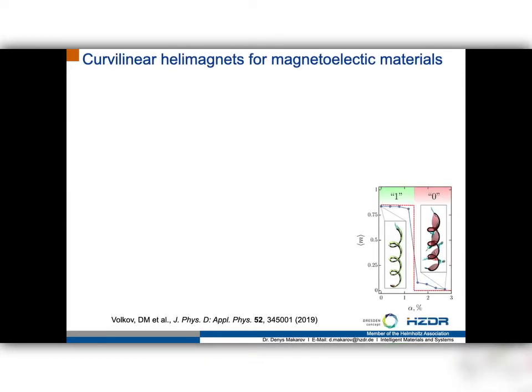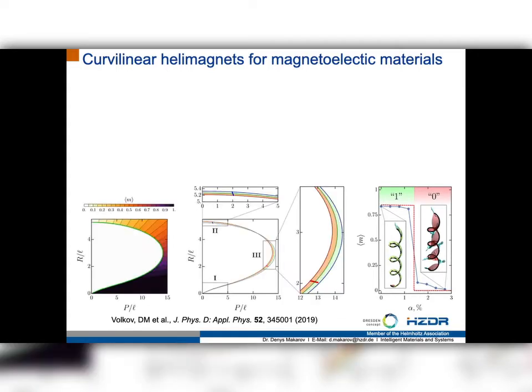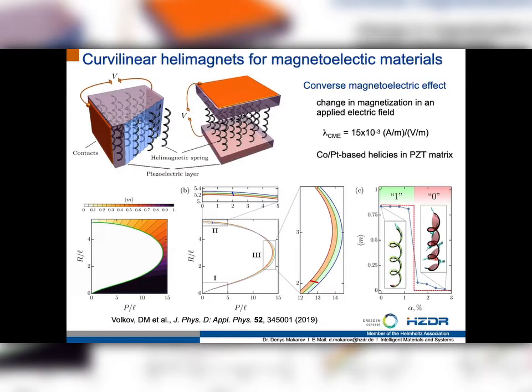For example, if you think of encoding the 1 and 0, like bits of information, into the state where you have periodic and homogeneous magnetic states which have different average magnetization along the axis of this helix, you will be able simply to tune the geometry of the helix to the phase transition. And now crossing the point of the phase transition can be done by a tiny geometrical transformation of this helical wire, which we can do, for example, by embedding it into piezoelectric material or simply sandwiching your helimagnet between the piezoelectric materials.